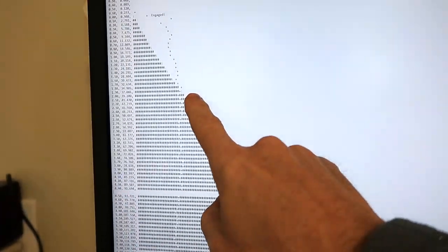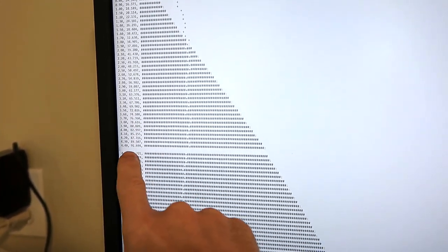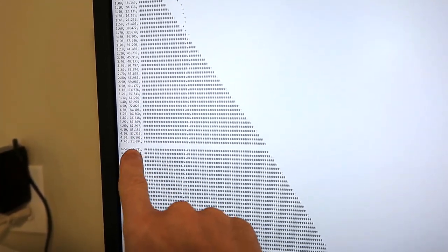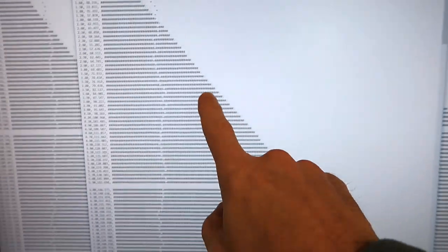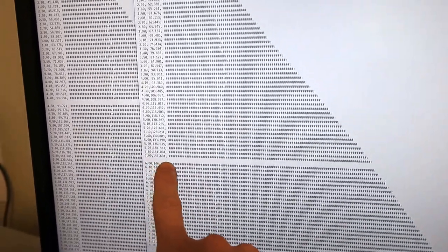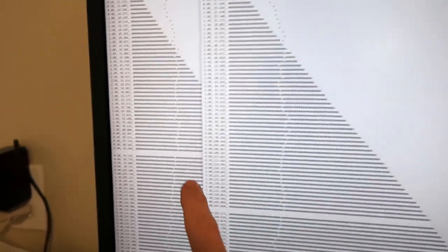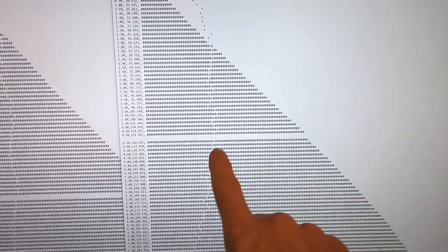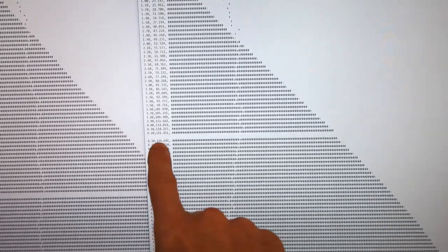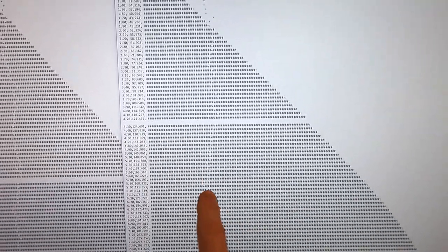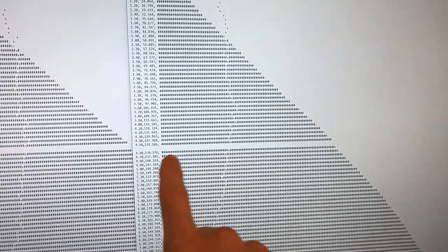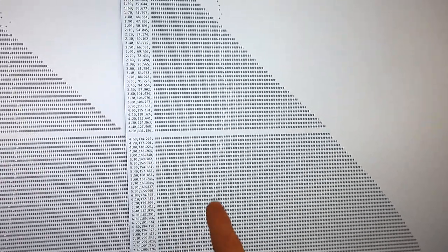Thinking further about suitability for a bow, I started to look at the yield curves. For the dogwood, the rate of increase started to slow down right around 91, 93 kilograms, which is to say we're starting to get into plastic deformation, as in damaging the wood. Whereas for the osage orange, that didn't really start to happen until we were about 143 kilograms, which suggests this may store a lot more energy, whereas this one is just bending. Then the hickory was 121 kilograms where it started to drop, although slowly. And the ironwood, 131 kilograms. So maybe osage orange makes the best bow.